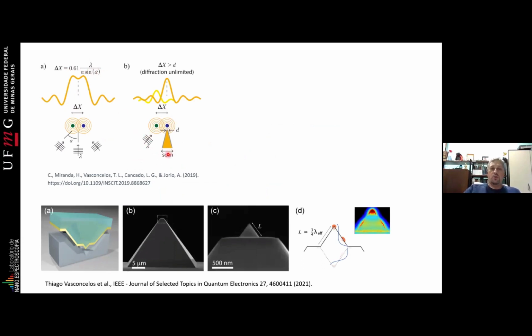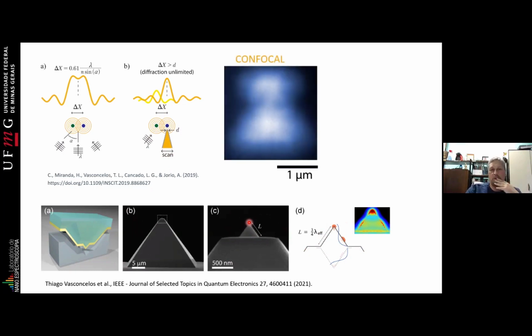You cannot resolve two-point sources which are closer than a distance of roughly the wavelength of light over 2. But what we do is approach an optical antenna, which we developed here. This is a gold pyramid, where we have plasmon confinement. We approach this optical antenna to our system, and the Raman signal is enhanced a lot, and the spatial resolution is defined by the size of the tip apex, which is between 10 and 20 nanometers.